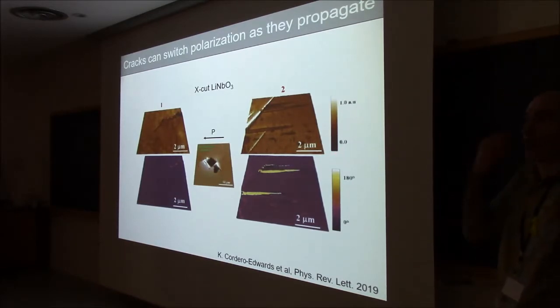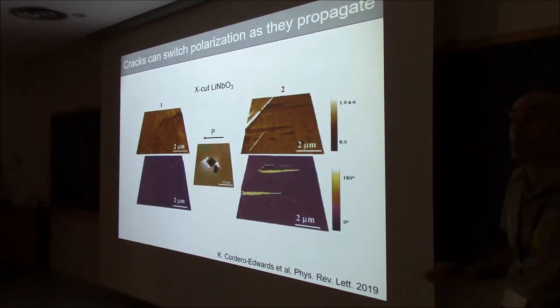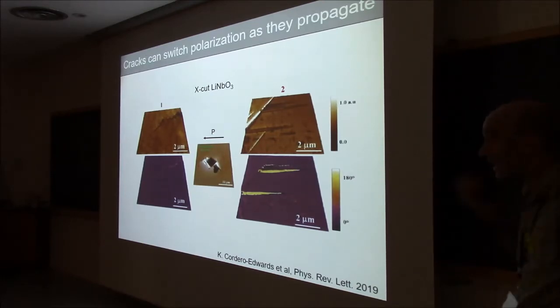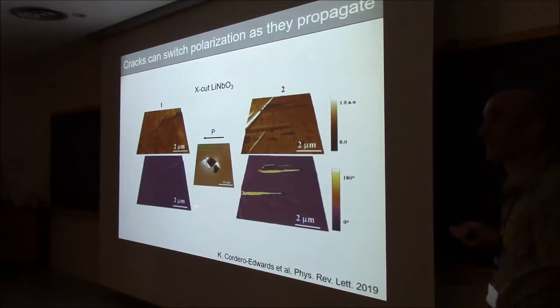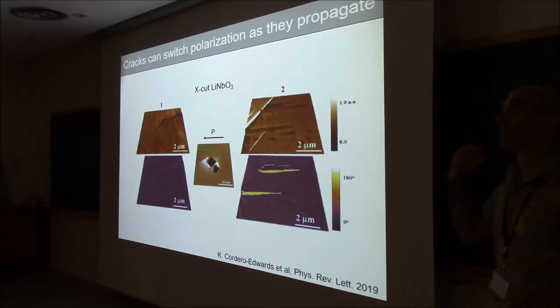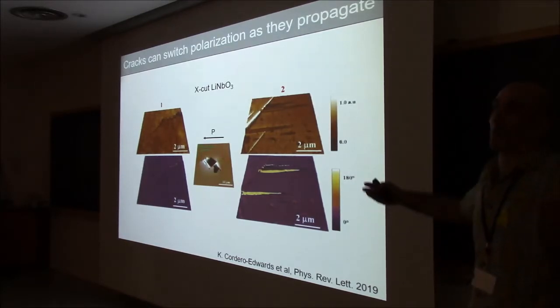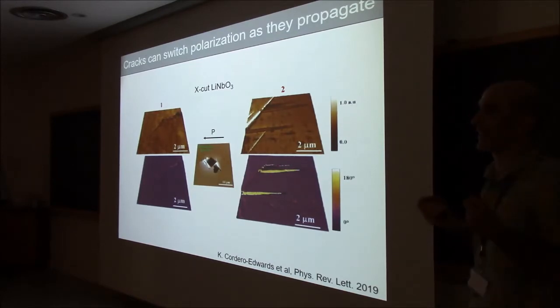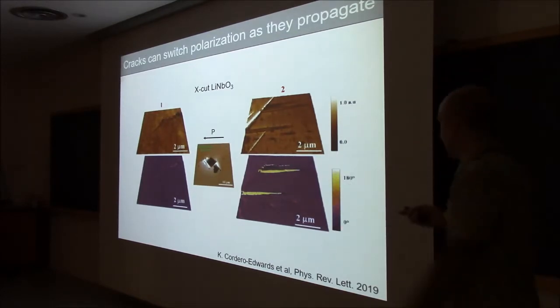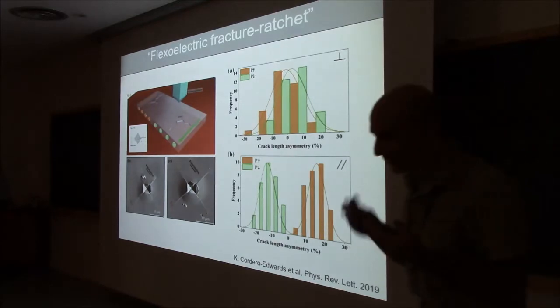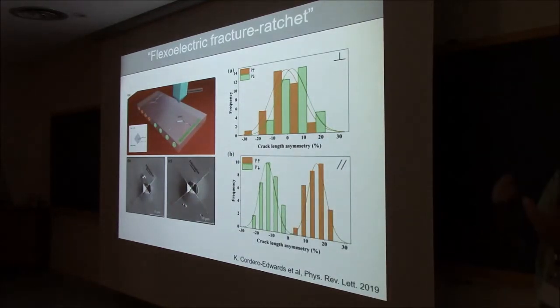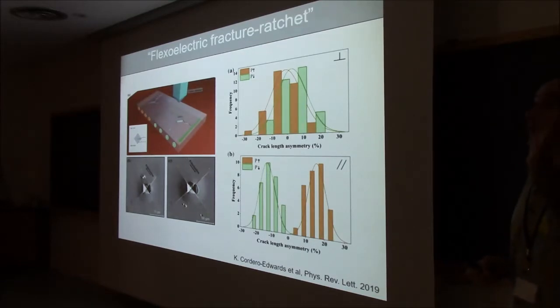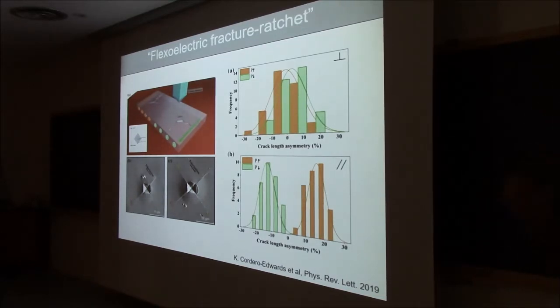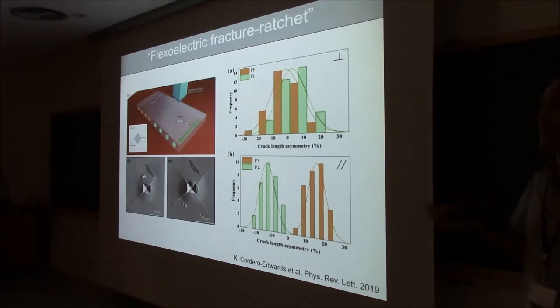Sometimes it doesn't work, or you don't see them. We don't know if it's because there is back switching. We think it's because there is back switching. In any case, if one of the cracks is switching as it propagates, some of the crack energy is being dissipated in the form of ferroelectric switching, which means that the crack has less energy available to propagate. And therefore, the crack that propagates against the polarization doesn't go as far as the crack that travels in favor of the polarization, which means that fracture physics in polar materials is asymmetric.